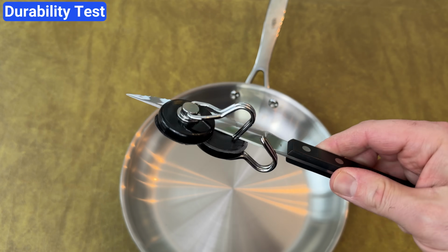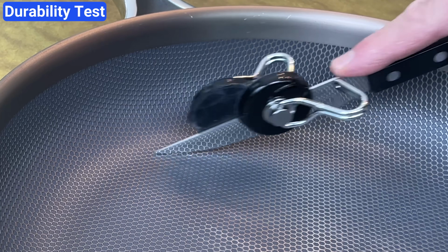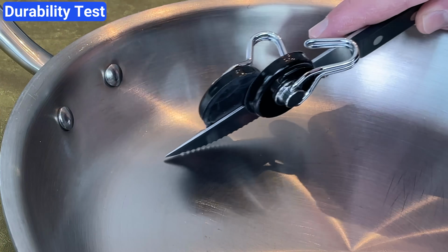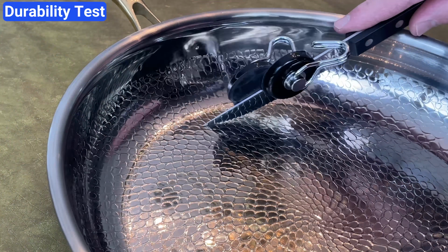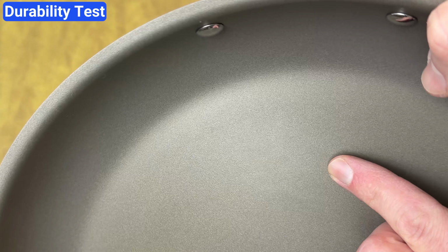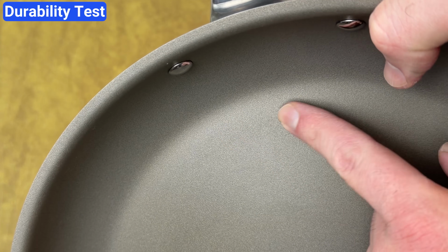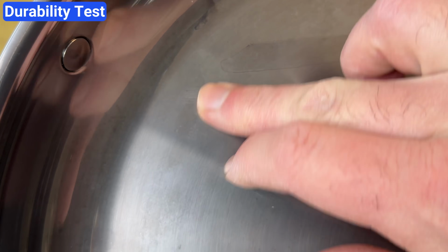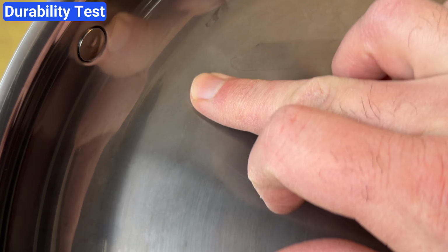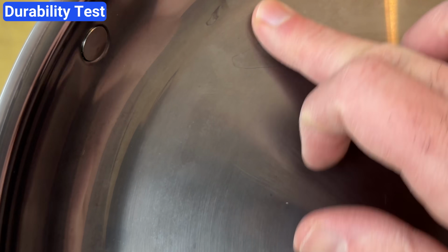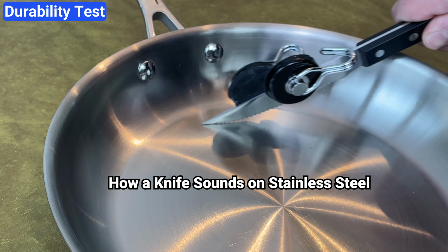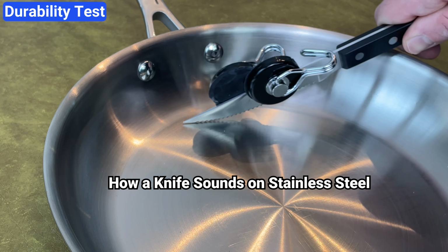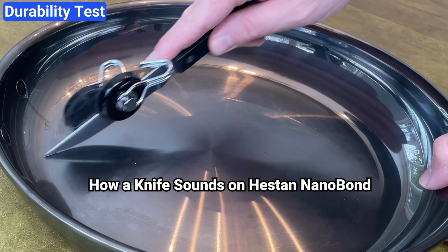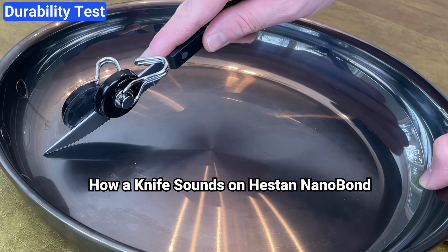Next, I took a serrated steak knife, attached 2 magnets weighing a total of 130 grams, and rubbed it across each pan 15 times. Viking had 0 scratches or damage. Hestan had minor rub marks similar to the spatula test, but the surface underneath was completely smooth. One thing I noticed is that the knife was much quieter on the Hestan pan compared to the others. The surface is so smooth and hard that the knife almost glides across it.